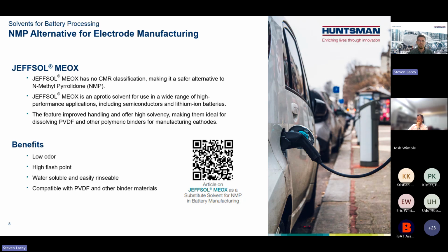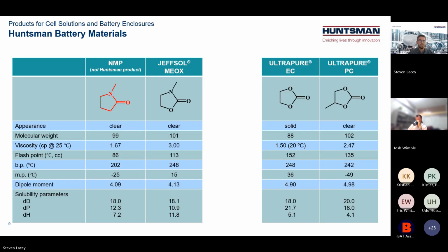And here I just have a QR code. If anyone is interested in a deeper dive into the technical aspects of MEOX versus NMP, you can just use the QR code here and go into a bit more detail in our brochures. So here's a breakdown of a property comparison between NMP and our MEOX. I also put the cyclic carbonates on here just for reference. And as you can see, the main difference in structure is actually this additional oxygen, which also improves the EHS characteristics, so health and safety, but also has similar solubility parameters to enable PVDF to be dissolved within.